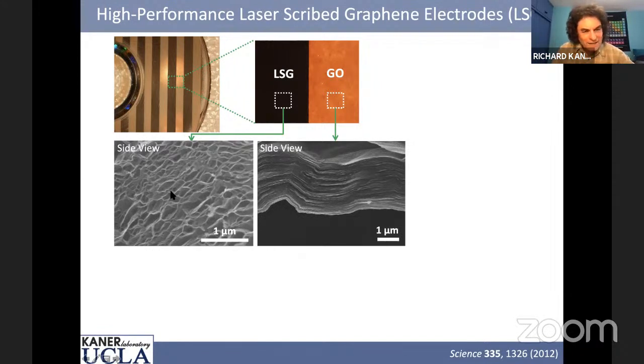So it's not quite a single layer material, but it can't be because it's ordered in the third dimension. In other words, it's connected, or maybe I should say it's disordered in the third dimension. But this is exactly what you want. And the reason we know it's a fractal is because you can measure that high surface area. You can get down to that level.